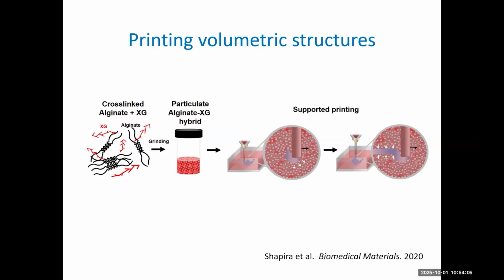What we've done here is develop a way to have a lot of nanoparticles within this glass cup, and the needle from the printer goes through these particles and deposits the material, the liquid or the collagen fibers, the patient's own material, in place. After it is heated to 37 degrees and solidifies, we can add another molecule that will dissociate the nanoparticles, and we're left only with the printed tissue. With that, we were able to print nice structures like that.